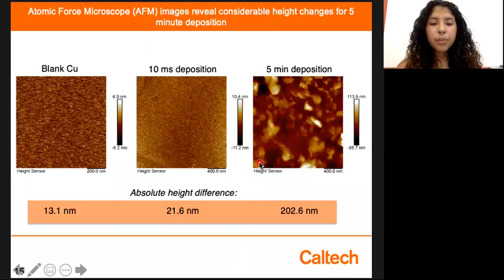To further support this hypothesis, we took atomic force microscope images and saw that after a 5-minute deposition, there is a considerable height difference. If we take the average of these heights, we see that the film does indeed become thicker, with a 150 nanometer difference between a blank and a 5-minute deposition.